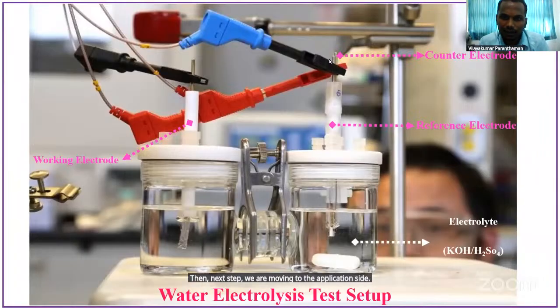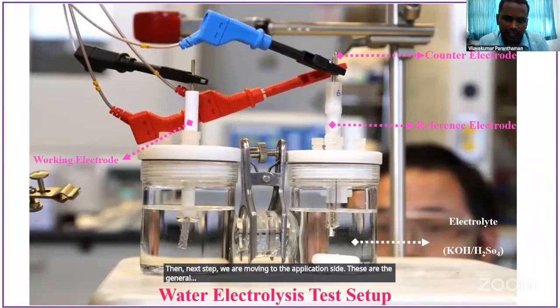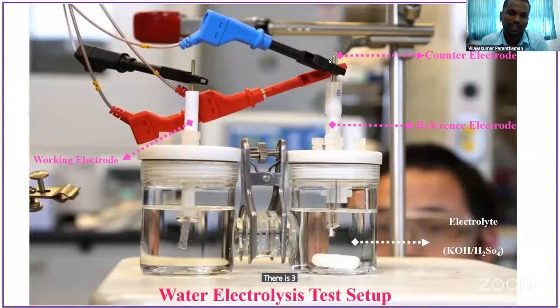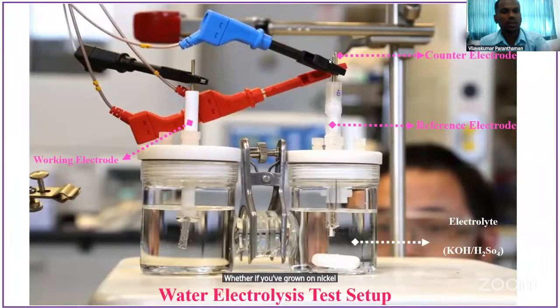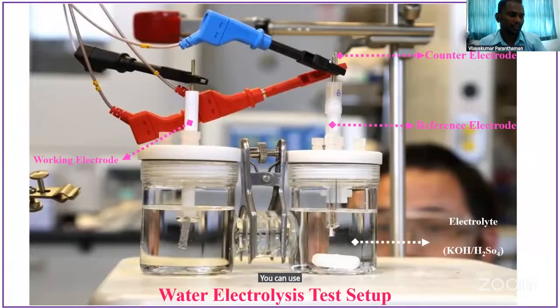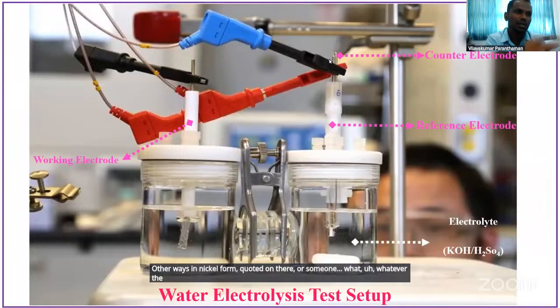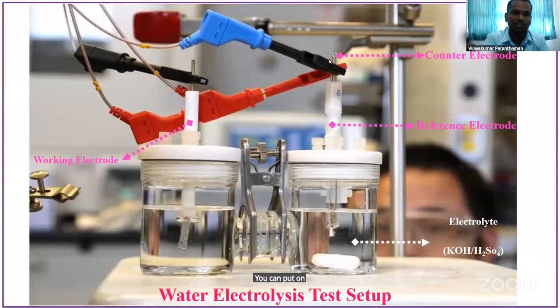This is the general traditional water electrolysis setup. There is a 3 electrode setup. The first one is the working electrode. The working electrode consists of your material. If you grew it on nickel foam, then you can use it directly as the working electrode. If you prepare it as a powder material, you can use a glassy carbon electrode, otherwise nickel foam coated on the side, whatever geometric area you need, then immerse in the solution.